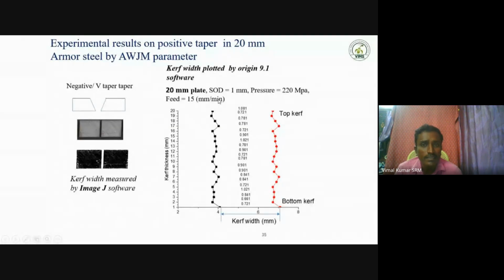In the same condition for the 20 mm plate, we can follow this kind of shape that we achieved. It's a negative or V taper. From this reading, here also we can measure 20 readings, one for each mm of thickness, by ImageJ software, and we plot a graph. Here also the exact shape of the cut surface is visible.